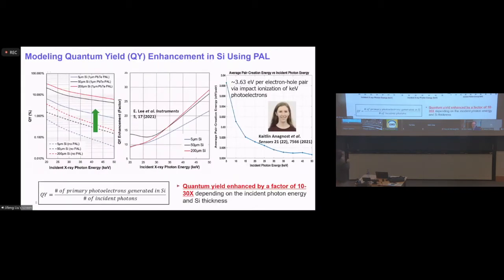And basically, Eldred further did some simulation comparing the silicon pixel's response to hard X-ray photon detection without the PAL layer and with the PAL layer. Same color means the same thickness of silicon absorber. So you can see, sure enough, a factor of 10 to 30 increase in detection efficiency, which is quite dramatic, because you can integrate this very thin layer in a very facile approach, but the effect is very strong. So in this case, this quantum yield is like the number of primary high-energy photoelectrons you produce per incident photon. And then eventually, this high-energy electron will further impact other valence electrons, starting an avalanche or cascade process, and produce more.